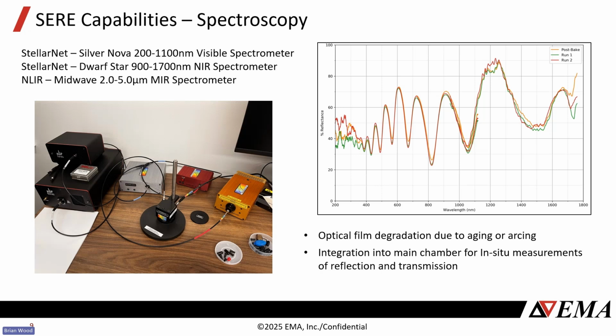So we're able to do periodic reflectance measurements while we're irradiating it. That gives you the in situ change or degradation of your optical coating as a function of dose that it would be receiving from our electron sources. Our electron sources go up to 100 keV, like I said. So the aging can only really be done to these thin films, but this is something we've done in the past, and that's just one use case of these spectrometers. It's just something that we've been able to incorporate with some of our past projects that I wanted to let you know about.